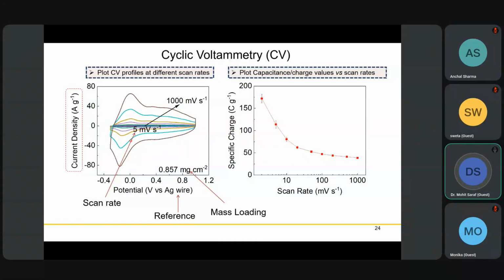At different scan rates, for example in this example, you are going from inside to outside, ramping your system at 5 millivolt per second to 1000 millivolt per second. So it's a scan rate. And always put how much mass loading is there on your cell, because it's very important to mention the mass loading on your system. It gives a clear implication whether it's a high mass loading or low mass loading, as reviewers often ask these questions, which can sometimes lead to rejection.